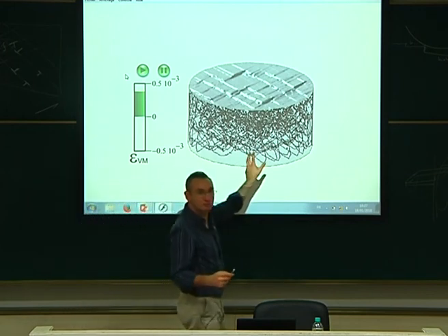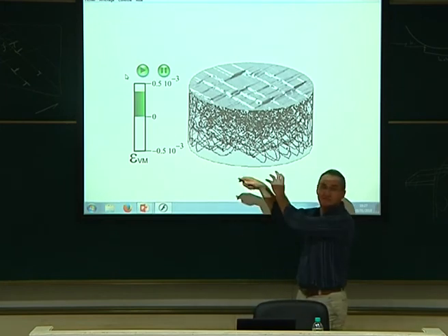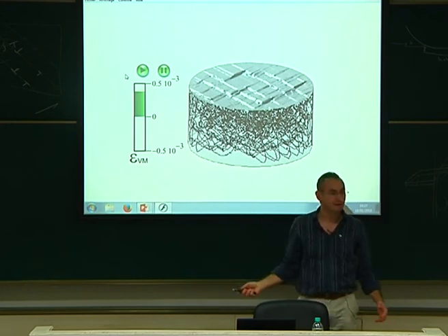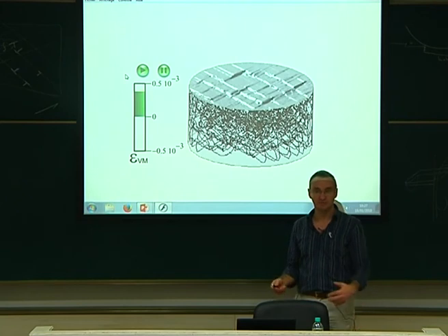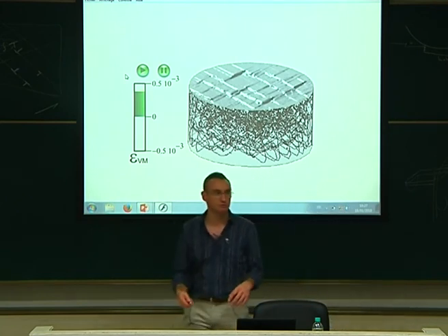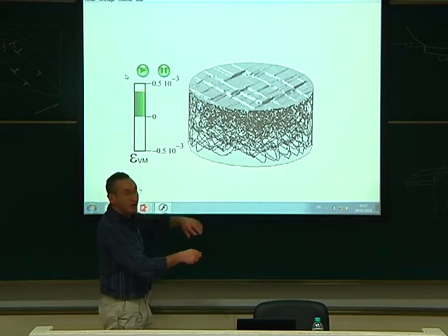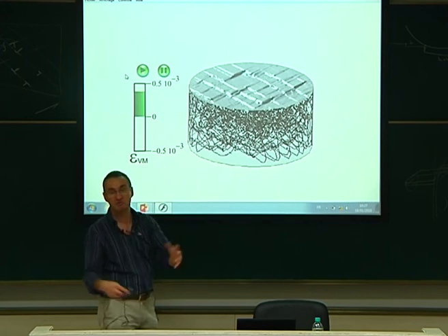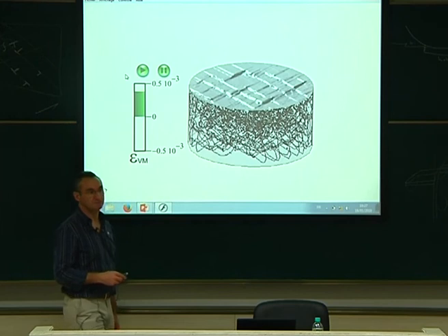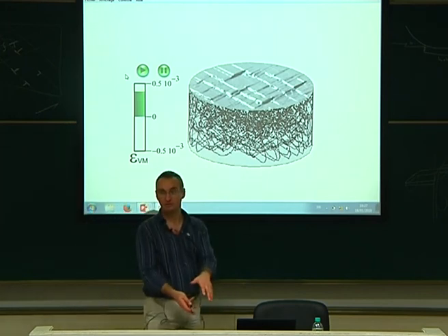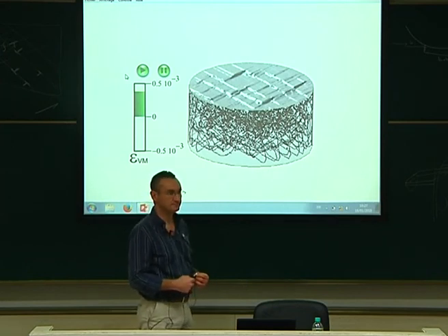What I gave you here is a kind of summary of the PhD. At the beginning, we were not so smart. We put 12 dislocation systems, we put loops everywhere, but we realized that we don't need that. A single source is enough, actually. But this took a year to figure out that we could take only a single source. If you take the 12 source system, you will have a lot of debris everywhere, but for nothing. They don't participate in the irreversibility. Tomorrow I will put those systems for the crack propagation, and you will see what they do, but not much effect. Yes?